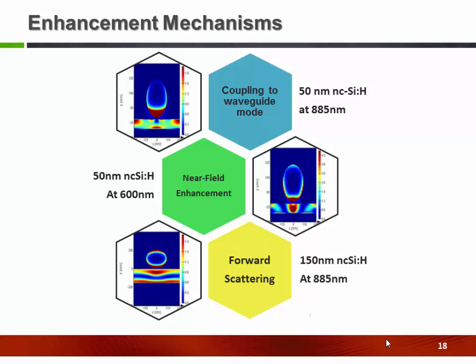Generally, if I want to summarize why I have seen this performance, I have seen three mechanisms in my devices. One of them was the coupling of the incoming light to the waveguide modes. For example, I have seen it for 50 nanometer nanocrystalline silicon at 885 nanometers. The other one was the near field enhancement, and the other was forward scattering. These are a combination of mechanisms.